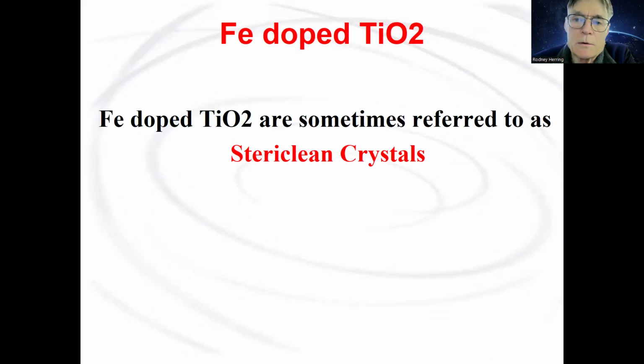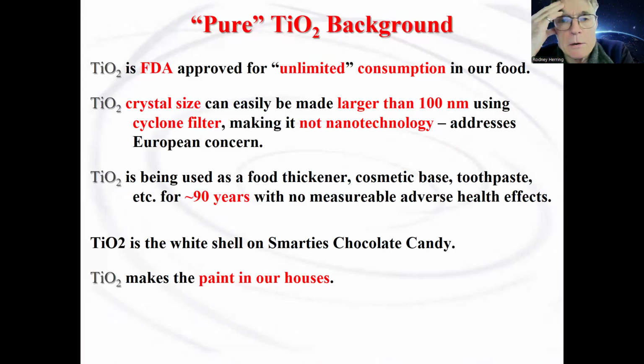These iron-doped titanium dioxide crystals are sometimes referred to as steri-clean crystals. In background, they're based on titanium dioxide, which is FDA approved for unlimited consumption in our food. My crystals can be made larger than 100 nanometers using a cyclone filter, so it addresses the nanotechnology issue that's a European concern. We have been using titanium dioxide as food thickener, cosmetic-based toothpaste for around 90 years with no measurable adverse health effects. A good example for food is the white shell on the Smarties chocolate candy. In addition, titanium dioxide makes the paint in our houses, so it's ubiquitous.